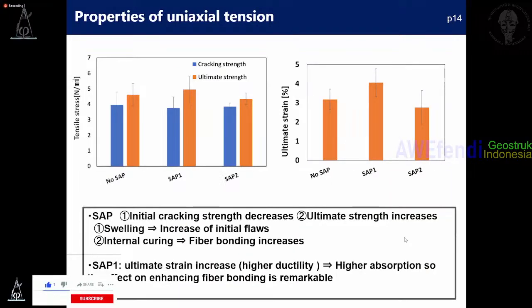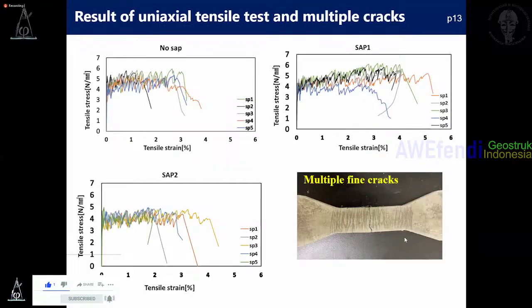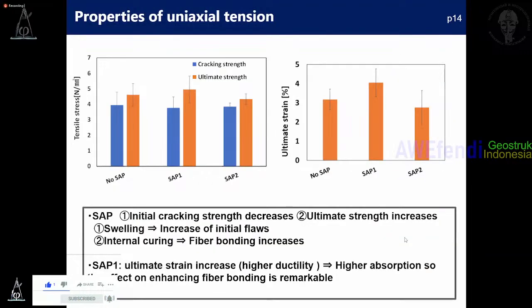And then from these graphs, we compare the cracking strength and ultimate strength for these 3 cases. These are all at SAP 0.3%. And you can see the cracking strength is a little bit reduced. But for SAP 1, you have increased ultimate strength and ductility. SAP 1 increased significantly compared with the no SAP case, but SAP 2 reduced a little bit.